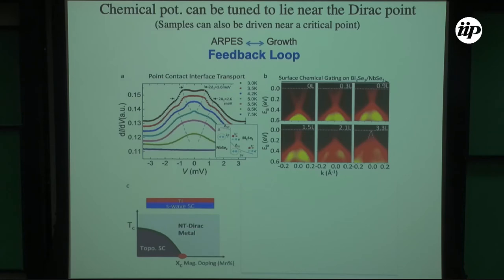There's not much overlap. So when you do that, you need a momentum transfer for the pairing. In other words, even though the TC is high, the induced TC is way too low, the proximity effect is way too small, that drops it probably below 4 Kelvin or something, then we don't see it. So we have a paper in PRB where we documented that if you take a BSCCO sample and put topological insulator on top, you don't really see that.